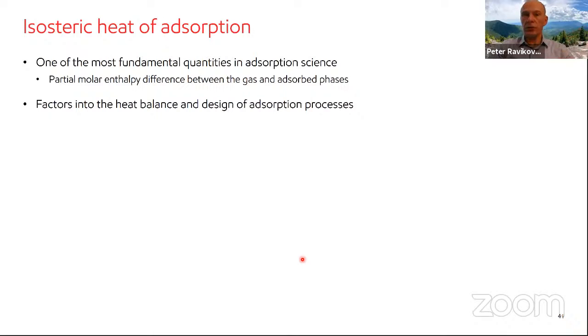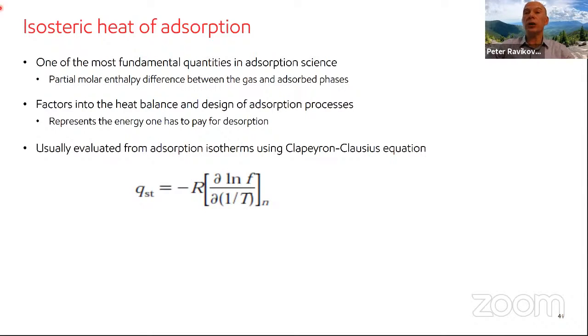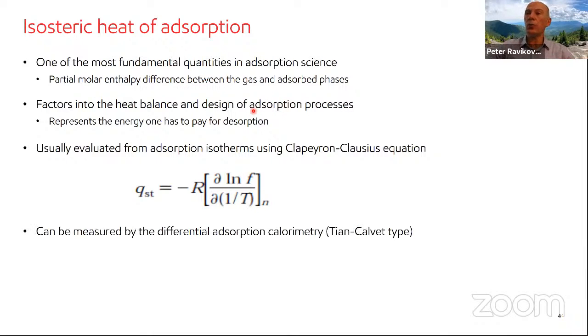So in the last part, we will talk about the heats of adsorption. As I mentioned, it's a very, very important quantity. It's a partial molar enthalpy difference between gas and adsorbed phases. It's actually one of the most important parameters in the heat balance and design of adsorption processes. So what are the ways to calculate the heats of adsorption? The typical way of doing it is to use a Clapeyron-Clausius equation, when you use a set of isotherms and then you use this rigorous relation. This is using fugacity to calculate the isosteric heat of adsorption, which is the negative of the enthalpy of adsorption by convention.